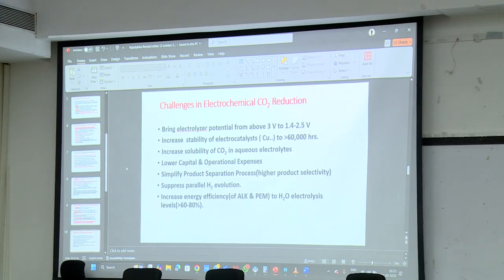Increase the solubility of CO2 in the liquid electrolyte. This is not a problem in water electrolysis. But when you go to CO2 electrolysis, the solubility of CO2 in aqueous electrolyte, especially at higher temperatures, becomes problematic. Reduce the capital and operational expense, product separation. Their efficiency is too low compared to water electrolysis. So that's the next challenge.